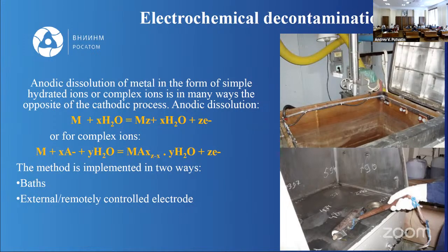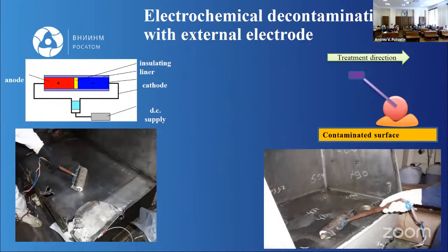If we apply an external electrode, you see it is like here, cathode and anode from this chemical tool, and all reactions occur in this water media, between your tool and the contaminated surface. Then you should remove just the thin layer of this liquid with some kind of special tool, like a vacuum cleaner, from the surface.